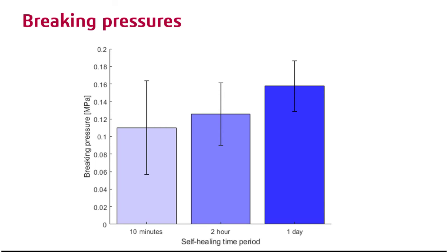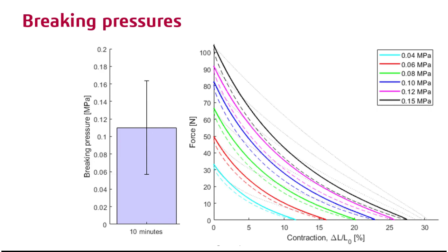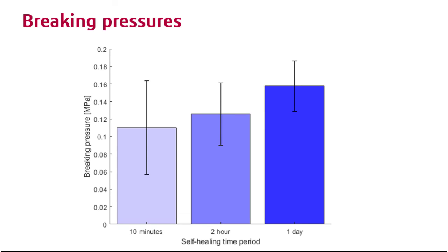Repeating these tests over several muscles and considering the different self-healing periods, we can analyze the breaking pressures. In this graph, you can see the results. Even after 10 minutes, our muscle can support 0.1 megapascals on average, which is a reasonably high value for the short time considered. It means that only after 10 minutes, this self-healed muscle can lift 5 kilograms, contracting the 5% of its initial length, for example. Of course, this breaking pressure increases as it does the self-healing time, reaching 0.15 megapascals after 1 day, which is a really good value.